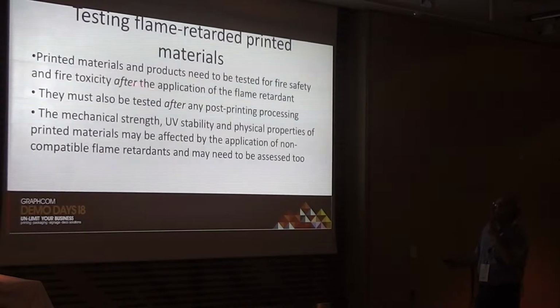Testing flame retardant printed material. Okay, I've already mentioned that apart from the flame retardation, the mechanical strength, the UV stability, and physical properties may be affected by the application of flame retardants. So you've got to take that into account. You have to be very careful. It is very important, as I said before, that the tests must be done before and after. Yes, the material providers do specify the compliance. However, when you are producing a final product, you are expected to test compliance as well.